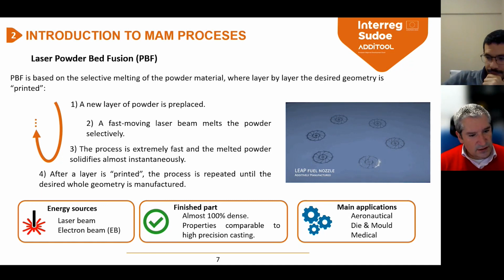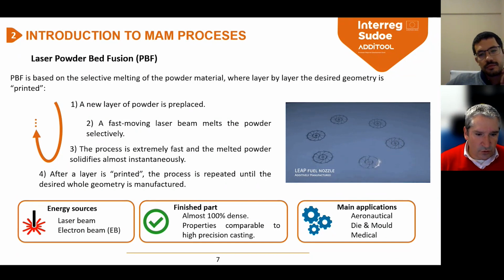The typical energy source, as I have already told, is the laser beam, and there are also some systems that use electron beam. It's not so typical, but the electron beam gives us a little more energy and goes a little faster using a higher grain powder. But on the other hand, the resolution of the part, the quality in terms of finishing, is not so good. So both techniques coexist. The process gives us a very good quality part if the process conditions are well selected, and we can obtain almost 100% dense parts, comparable with high quality castings.